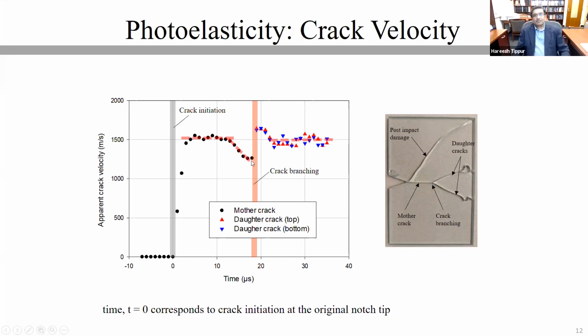So when the crack begins to slow down, at the end of that period, there is a crack branching event, and this branching event produces a sudden jump in the crack velocity, which again continues and settles down to this cruising speed of around 1,500 meters per second. So I want you to remember this signature: a constant velocity followed by a slowing down and a sudden jump in the crack velocity after branch. So this is going to be a pattern that I want you to recognize in future experiments